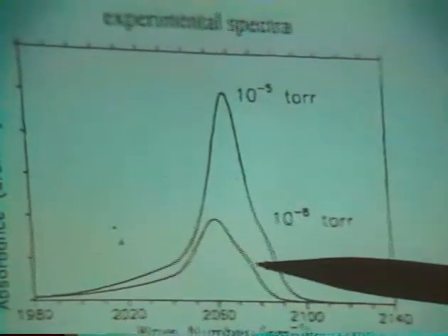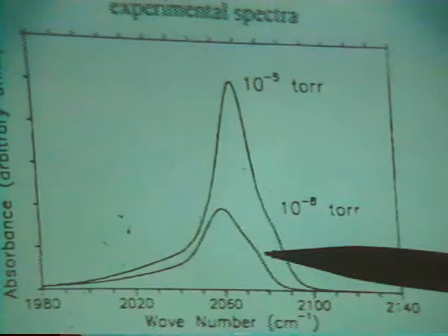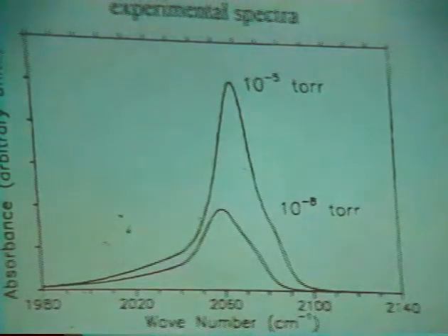The in-phase mode, when you don't have a complete layer, is there, weaker. It's been shifted up by the coupling, but not down because we're still in that highest mode. And so that gives a band here. And of course, the interest in that is because it looks like the spectrum here for particular coverage, the experimental spectrum. If we put 12 molecules on there, saturate the surface,